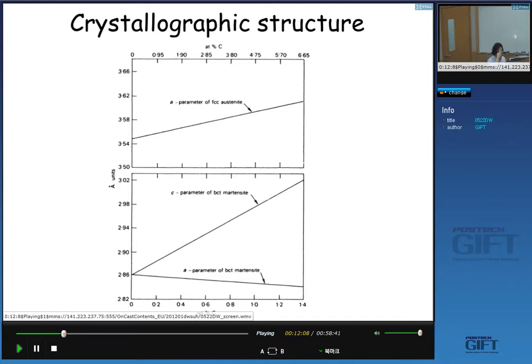One interesting thing when we look at the crystallographic features of the martensite is this: this is the lattice parameter of the austenite as a function of carbon. When we put carbon into the austenite, it stretches the lattice, and the degree of the stretching is not dependent on crystallographic direction. So when you add carbon, the lattice parameter monotonously increases without any dependency on the crystallographic direction. But